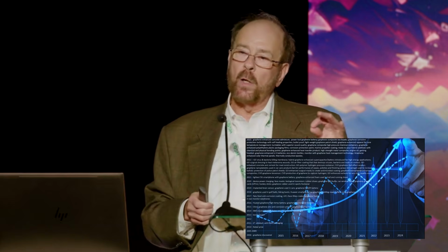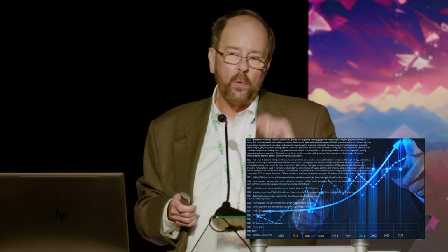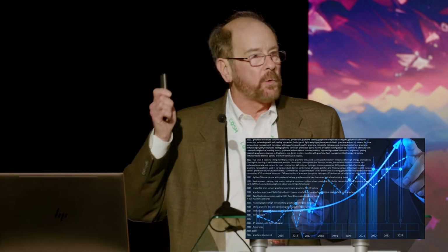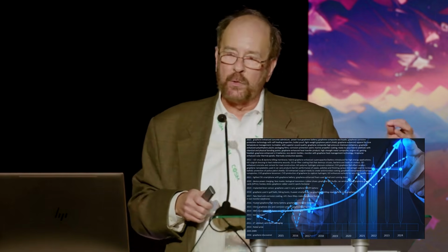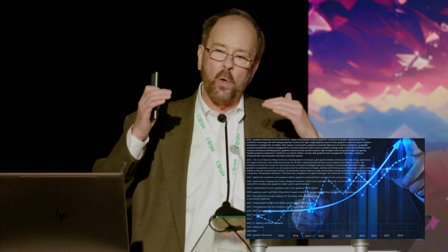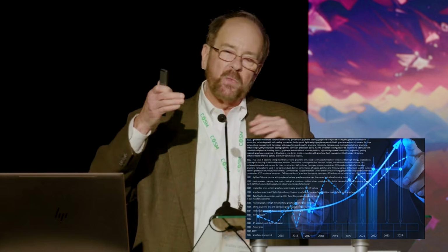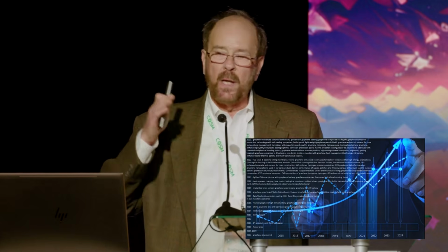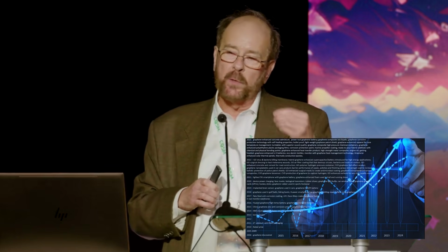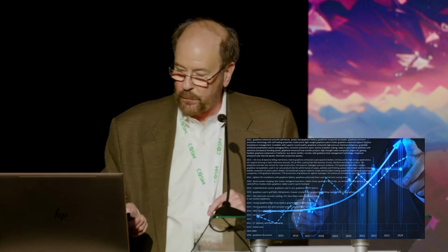And every year, we've seen the graphene usage in products growing. Last year, we were thrilled to see that on average, 1 new product was introduced every week with graphene. This year, we're seeing 1 new product being introduced every day with graphene. But it's been limited because there is no source for large, thin, and defect-free graphene flakes. Really what we've been using is this range of materials, things like graphene oxide, which is the separation of graphite in a harsh way that results in a carbon-oxygen bonding. The material has some nice properties to it, but nothing like real graphene. Then came along reduced graphene oxide, which tried to get rid of some of those oxygen defects, but still not very strong and not very conductive.